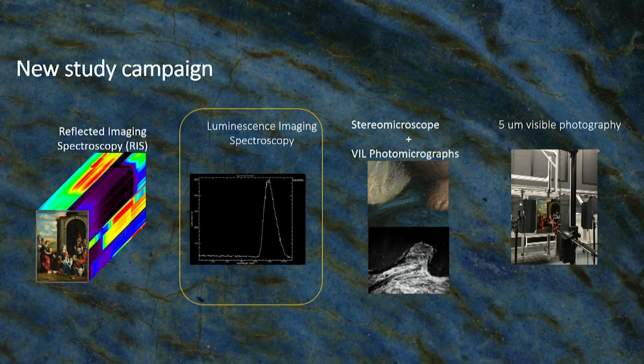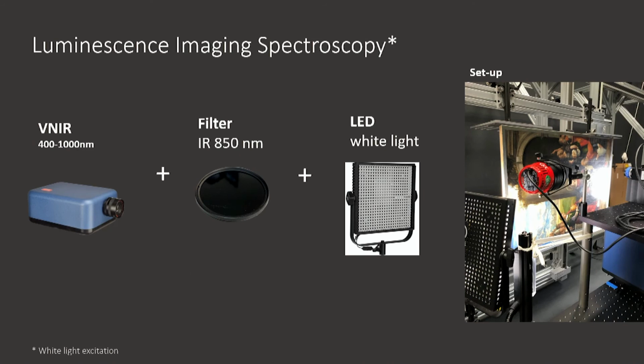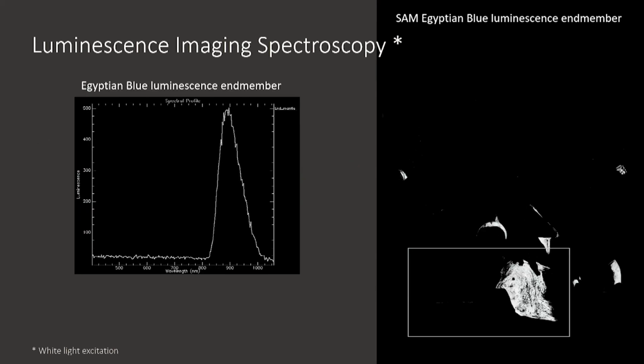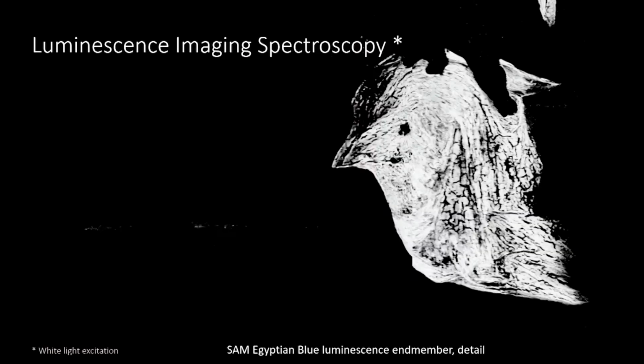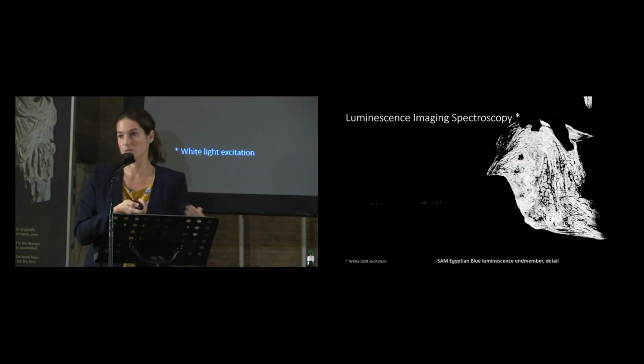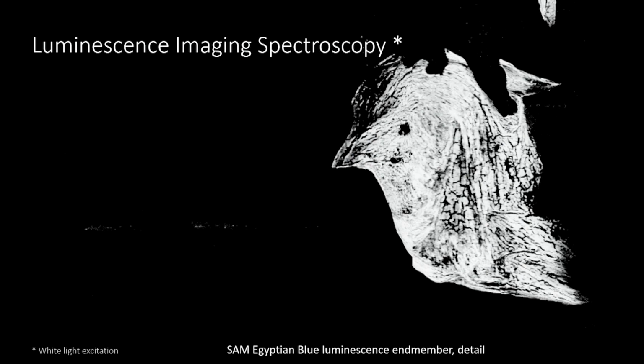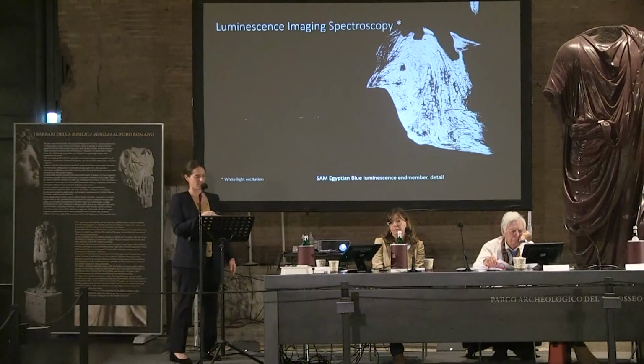Since we had the camera, the spectroscopy camera, the painting, and the setup and the time, we decided to try and acquire luminescence imaging spectroscopy. So we tweaked our setup a little bit, and we could obtain a clear luminescence spectra centered at 900 and map it on the surface. This technique has also a very high resolution, so we could zoom in and see some details that we had missed in VIL that we did before, like these 2 horizontal strikes.